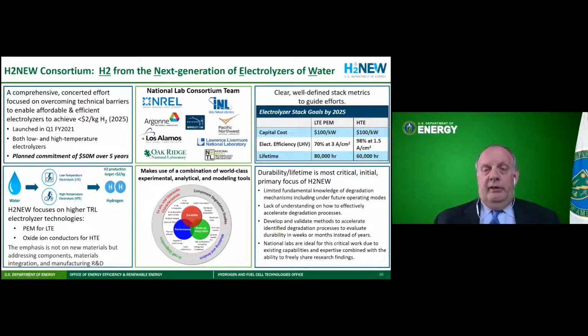They'll initially be looking at understanding degradation mechanisms when you integrate the electrocatalyst, the membrane, ionomers and all the other components into a membrane electrode assembly. And then when you start incorporating that with other components to make up a stack, and developing accelerated stress tests so we can understand the durability in a matter of weeks or months and not have to wait years.